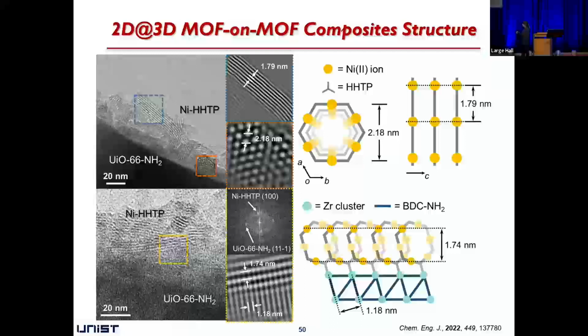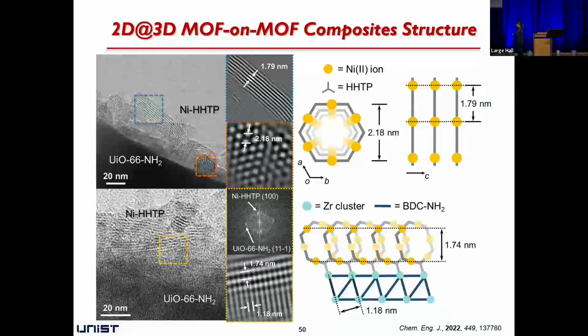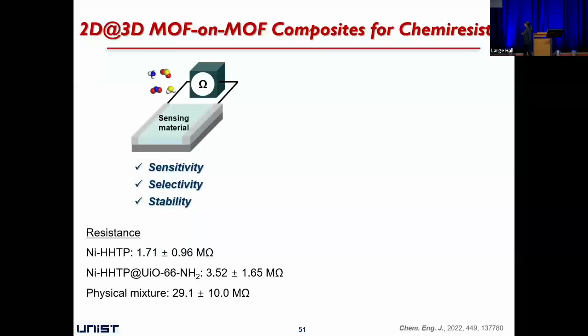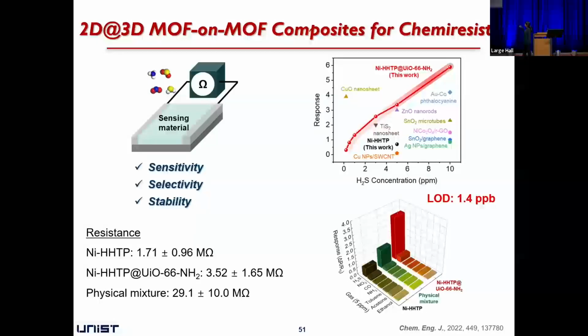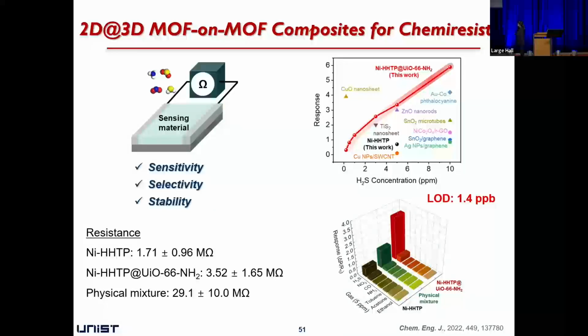Because of this interface, it modified the electronic structure, and it also showed a different HOMO-LUMO level. So when we applied this material as a chemiresistor for sensing hydrogen sulfide gas, this material showed superior response properties over other types of sensing materials. The limit of detection is only 1.4 ppb, and the selectivity is also very good.